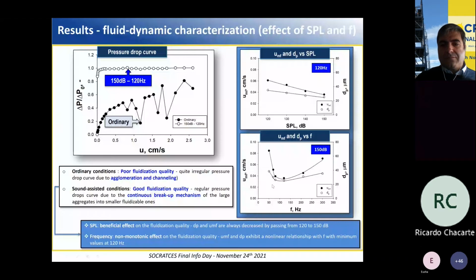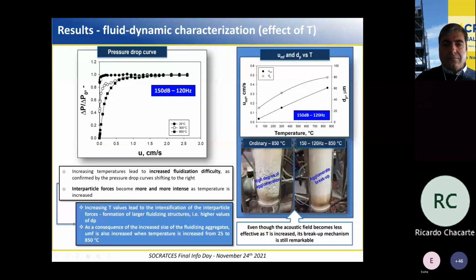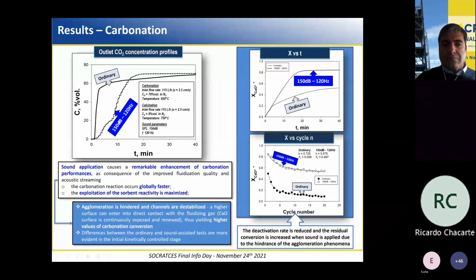Here you can see the comparison between the CO2 outlet concentration profiles obtained during the carbonation test under ordinary and sound-assisted conditions. On the right, corresponding results in terms of carbonation conversion as a function of time. It is clear that the application of sound is able to remarkably enhance the carbonation performances in terms of larger values of carbonation conversions. In particular, the application of sound makes it possible to maximize the exploitation of sorbent reactivity due to the better fluidization quality and in turn the better gas-solid contact efficiency.